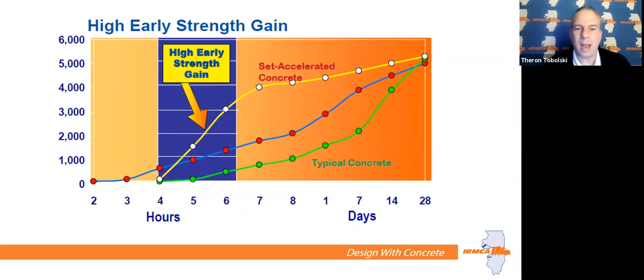You can see in the 7-hour range, you went from 1,000 PSI with no accelerator to a concrete that has accelerator, you're at 4,000 PSI. So instead of waiting days to open your concrete, you can open it in actual hours. So that's kind of the benefits of an accelerator. In cold weather or high early strength requirements, accelerators are used.